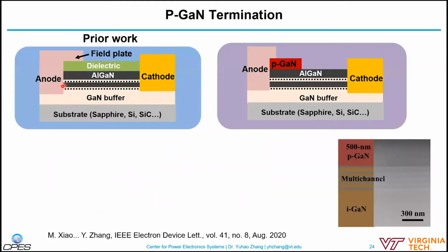Okay. So essentially, last year, we proposed to use P-type gallium nitride to manage the electric field and leakage current in this multi-channel diode. For example, here just shows the Schottky barrier diodes. And the traditional way to manage the electric field is by having a field plate at the anode side at the Schottky region. But last year we tried this using the P-type gallium nitride, essentially for the edge termination.